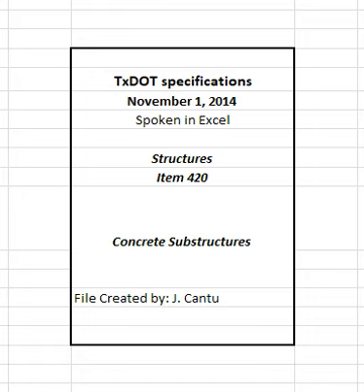Fill each part of the forms by depositing concrete as near its final position as possible. Do not deposit large quantities of concrete at one point and run or move the concrete along to fill the forms. Deposit concrete in the forms in layers of suitable depth but no more than 36 inches deep unless otherwise permitted. Avoid cold joints in a monolithic placement.